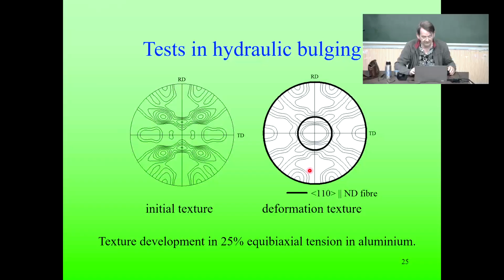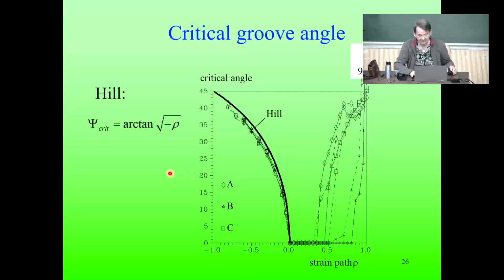I was doing for titanium in Belgium, in Leuven. Very detailed forming limit measurements were done. Now, let me speak about this. This is really important, the texture effect, so the polycrystal effect on the critical groove angle in this theory.